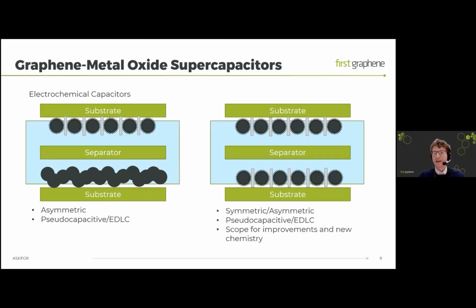So these metal ions in the metal oxide change oxidation state very quickly, and you can store more charge on the surface. It doesn't take as long as intercalation of lithium or any ions from the electrolyte in a battery or in the lithium ion hybrid supercapacitors. It happens much more quickly than that. And that's why it's called pseudocapacitive: it almost acts like a capacitor rather than a battery, even though there are chemical reactions going on. It doesn't rely on that intercalation.